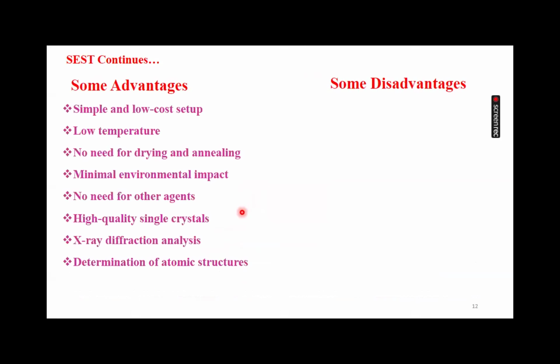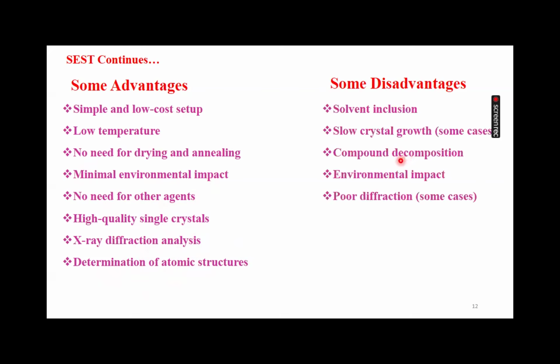The advantages are a simple and low cost setup, low temperature, no need for drying and annealing, minimum environmental impact, no need for other agents, high quality of single crystals, X-ray diffraction analysis, and determination of atomic structure was confirmed for NLO materials. Other disadvantages are solvent inclusions, slow crystal growth, compound decomposition in some cases of materials, environmental impact, and poor diffraction in some cases of materials.